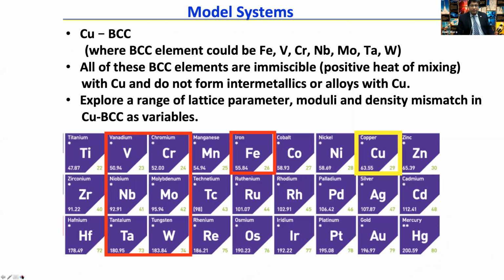And the model systems that we will use in this will be copper as an example for FCC, and we will pair it with a body-centered cubic element that can be, I gave one example of niobium, that can be moly, tantalum, tungsten, chromium, vanadium, iron. All of these are body-centered cubic elements. Many of them are refractory elements. And the key is that all of these, if you look at the phase diagram of binary copper with iron or copper with moly or with niobium and so on, they are all immiscible and have positive heat of mixing.